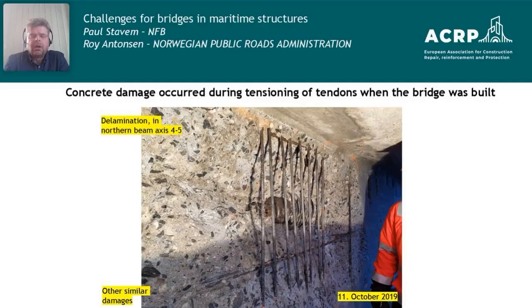And I think this box here is called a coupler in English, and it's totally revealed because of the concrete falling out. What happened here is that we went to see this immediately, and because we have a lot of routine inspecting damages on bridges, we could see that this delamination didn't occur recently. It has been there since the bridge was built. The surfaces here are dark and carbonated, and this is old concrete surface, right? So this delamination had been here since the bridge was built, and we suspected something happened when they built the bridge, and it was not recorded properly there in 1966 when it was built.